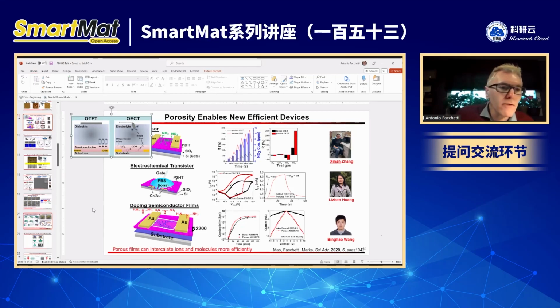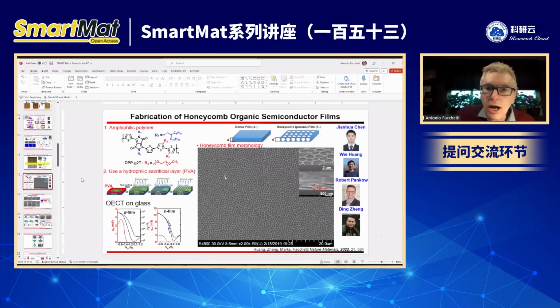But when we go to devices like this, where there is no polystyrene and you have a honeycomb, see here the hysteresis is quite reasonable for an ionic-coupled device. In the honeycomb film the hysteresis is much lower compared to the dense film. So when you go to a film which is porous and has a little hydrophilicity, then the hysteresis can be suppressed quite a lot. It's still not ideal. You still have some hysteresis in the subthreshold region, but it doesn't affect it. You can make good devices.